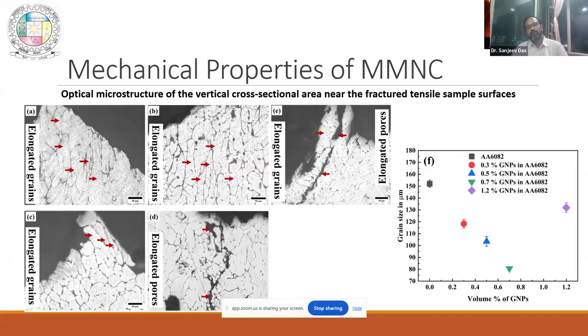We measured the grain size of those elongated grains. Now what we are seeing is that with increase in the nanoparticles, the grain size is decreasing. So if the grain size is decreasing, that means these particles are doing something. GNPs are not a good heterogeneous nucleating site that will create a lot of nucleating sites like titanium boride. Earlier I have shown you, but it could be working as a pinning agent. Suppose one grain is trying to elongate and grow, then these are not aligned to grow. So that is one of the possibilities.